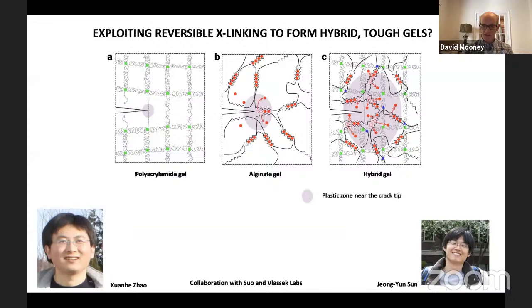And so what he and Jeong-Yun Sun, a visiting PhD student in the labs of two of my collaborators at Harvard, Suo and the Vlassak labs, were able to demonstrate together, or propose initially, was that having a combination of dissipative, stress-relaxing bonds within a material combined with covalent bonds could lead to significant toughening. The basic idea is if one has a typical covalently cross-linked hydrogel like a polyacrylamide gel, as one starts to stress it, one puts a significant stress on individual bonds. The stress becomes so great that those bonds fail, and then you get stress propagation throughout the material.